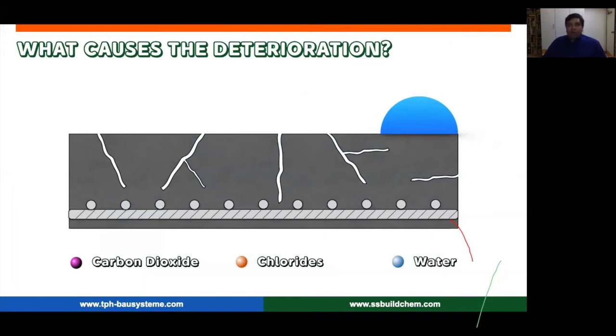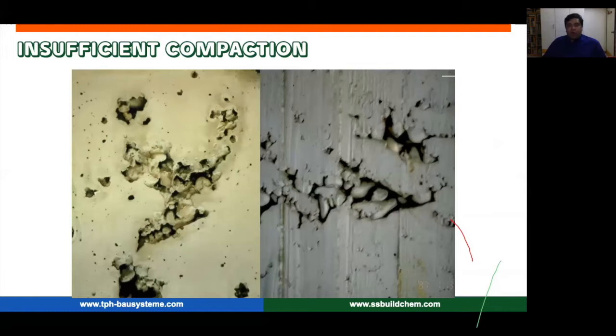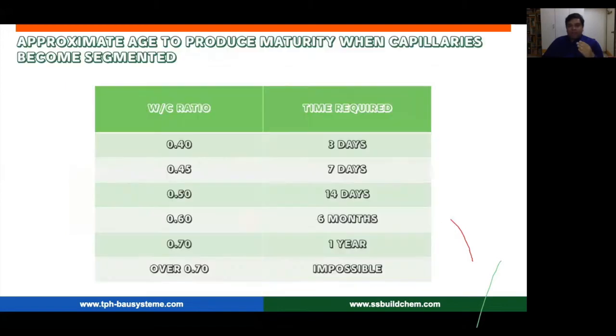Similarly, what causes the deterioration? If your concrete base is a bit permeable, it will allow carbon dioxide, chlorides, and water to slowly reach your reinforcement. And it is this that actually causes damage to your structures. That is on a micro level, where there is ingress of water and carbon dioxide through your concrete. But on the macro level, also, things like honeycombing allow very easy access for water and other problem-causing ingredients to reach the reinforcement much, much earlier.